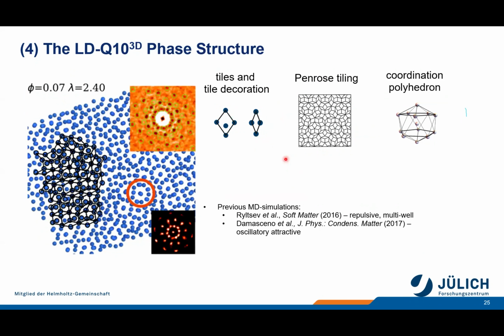We're now coming to the 3-dimensional quasicrystalline structures. They consist of planes with tiles, and the planes are stacked on top of each other. Here the 2 tiles for this 10-fold rotational symmetry are a thick rhomb or fat rhomb with a decoration here. This would be the small distance, and the edge would be the large distance. And this would be a thin rhomb, where the small distance would be this. This packed together is the Penrose tiling, which we had at the beginning.